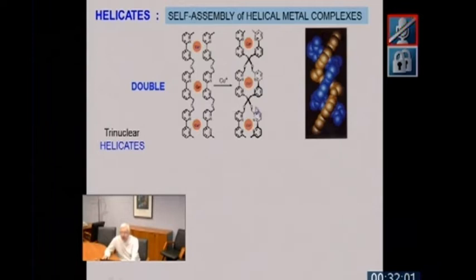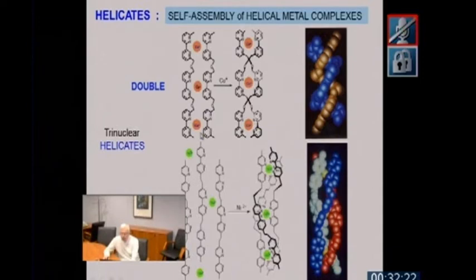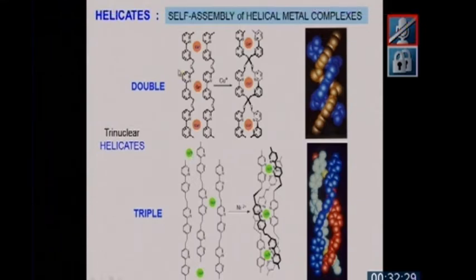So let me just show you that, in fact, this strand, which contains bipyridine subunits, and this could be the analog of a trinucleotide, interacts with copper(I) and automatically generates a double helix. This is a crystal structure of the double helix obtained. You can make triple helices by taking not copper, but nickel or cobalt or iron with this strand here, which is somewhat different from this one, a little bit modified, and this assembles to give a triple helix. So you see here that by spontaneous but very well directed assembly of these strands plus the metal ions, you get either a double helix or a triple helix.